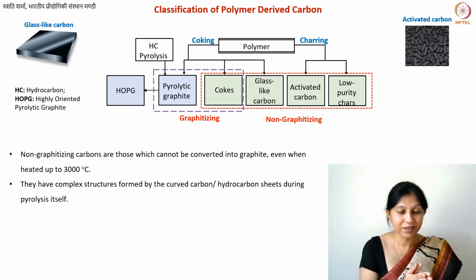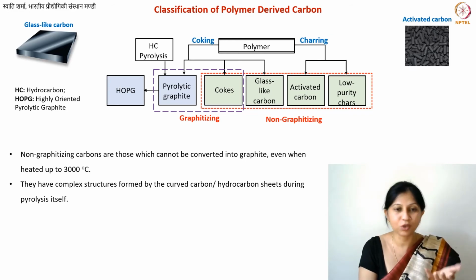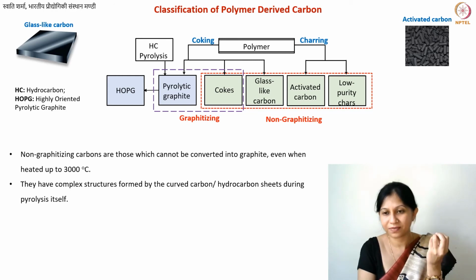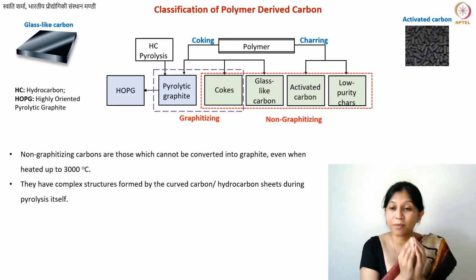And these curved structures, for example fullerene, may be curved carbons, not completely spherical structures, but curved structures, tube-like, or just some very, very wavy sheets of graphene. Now, however, the point is that once a completely curved or highly curved structure or a complete sphere is formed, that requires a very high energy to open. So the energy of formation of fullerene itself is pretty high.